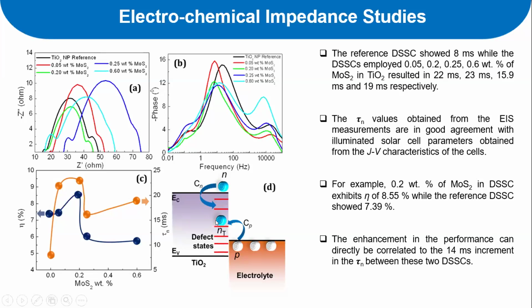Once the electrons are captured and trapped in the band gap of the titanium dioxide, there are positive holes in the electrolyte that can also be captured by the trapped states. Then positive as well as negative charge carriers are captured and trapped in the defect states. Then that goes to recombination and we have a charge carrier loss. So we have lost the carrier. So overall, we have reduced current as well as reduced photo conversion efficiency.